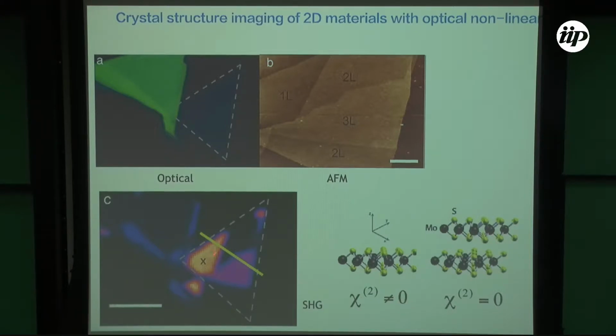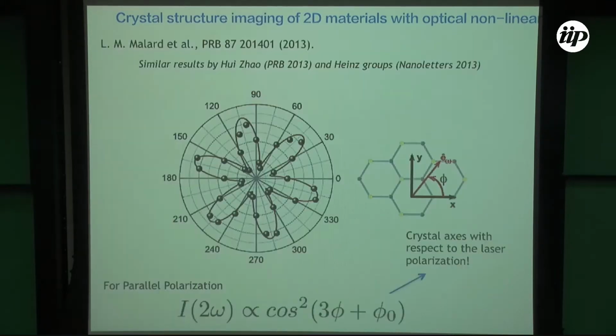Okay, and this absence of second harmonic emission can be understood by looking at the symmetries in monolayer and bilayer MoS2. In the monolayer you don't have inversion symmetry, so it can generate second harmonic. But in the case of the bilayer MoS2, you have an inversion symmetry in the middle of the 2 layers. In this case the chi2 is equal to 0. So that's why we don't observe second harmonic generation. So that's one thing: only an odd number of layers is going to generate second harmonic emission.